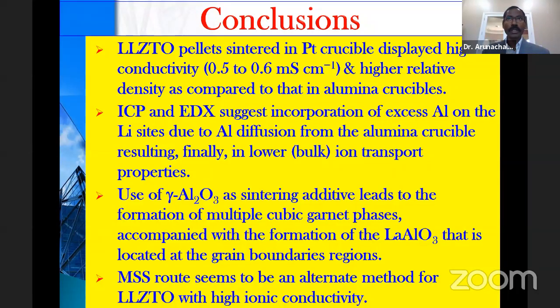So, aluminum coming from an alumina crucible, if the crucible is alumina, or like in other studies, if you use alumina powder as a sintering aid, aluminum can easily diffuse into the bulk, which would certainly occupy the lithium site. So that means lithium ion conductivity is going to be lower. So one has to be really careful.